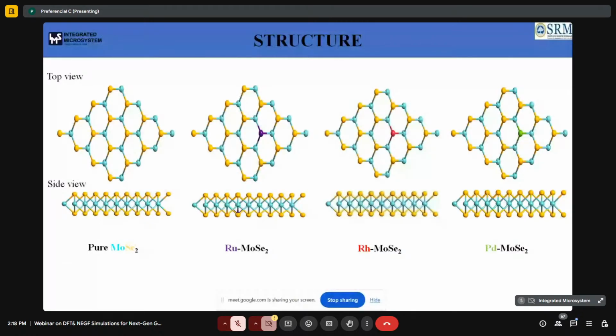Here we have replaced molybdenum with the dopant, as well as selenium, and systematically analyzed them. But out of those, only the selenium replaced system is showing high stability. So for further analysis, we consider only the selenium replaced by a dopant. That system alone we consider for the remaining analysis, that is, the gas sensing analysis.